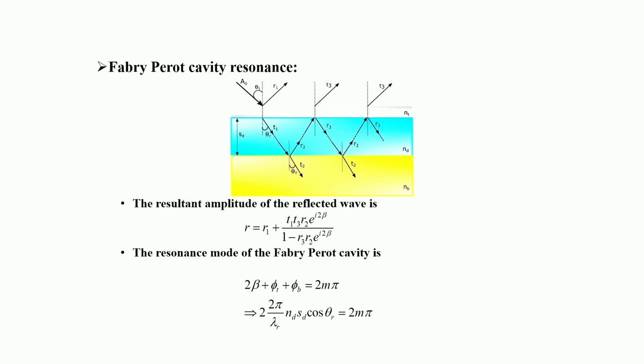One such structure is a simple Fabry-Perot cavity where you have a top metal and a bottom metal. This is a thick metal so that the transmission is suppressed, so it's a 100% reflecting surface. And the Fabry-Perot modes can be calculated easily, so that we can design this structure for particular wavelength regions.